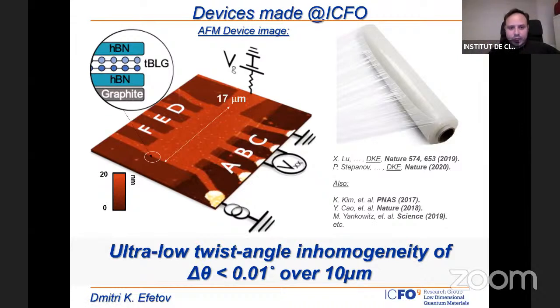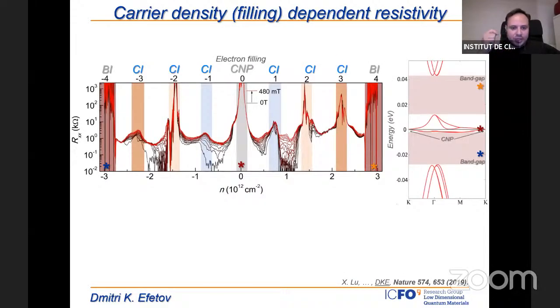What we do in our lab is we make those devices and then measure transport. We measure resistance as a function of temperature, magnetic field and carrier density. I want to show a typical measurement which we perform. We measure the resistance of the device, and we change the carrier concentration by tuning the gate. What it means is that we can start with a band completely empty, at this limit here where the carrier concentration is negative. In this region, we find a very strong insulator. Resistance goes to the megaohm. It's really insulating, and we explain this as the band gap, which we observe in the band structure here.